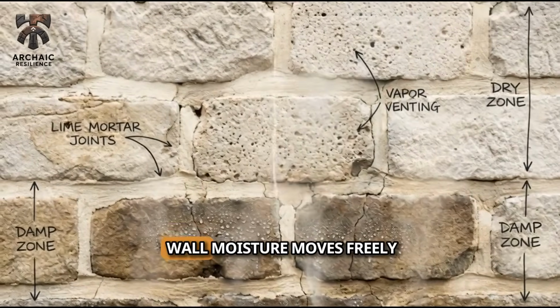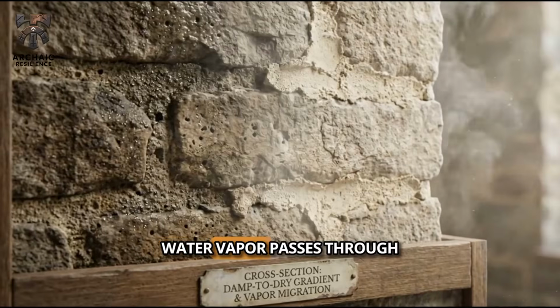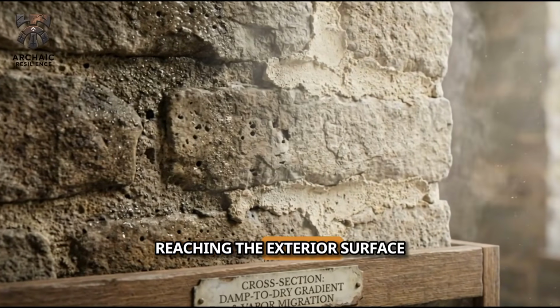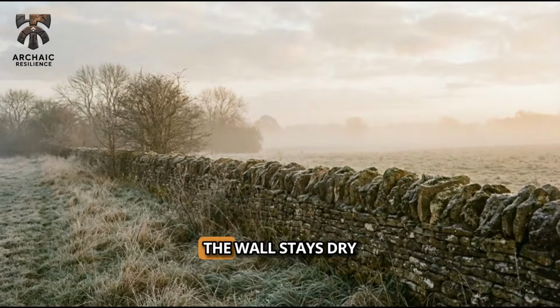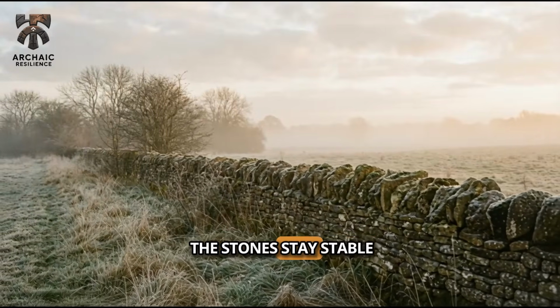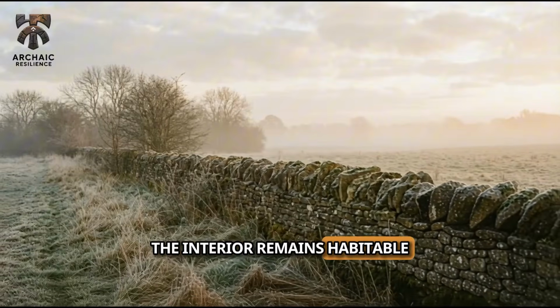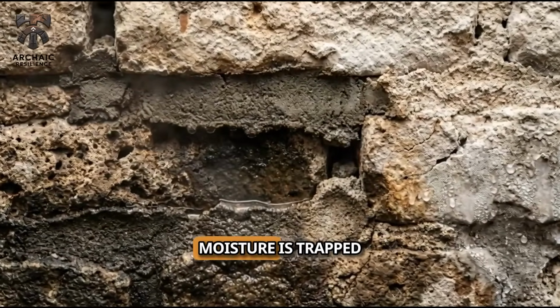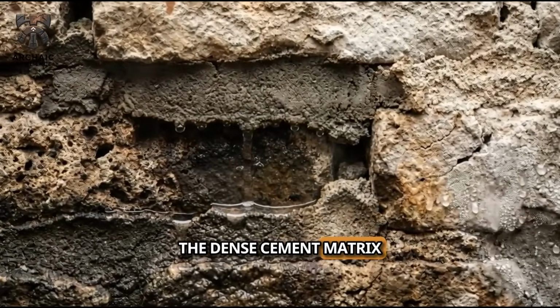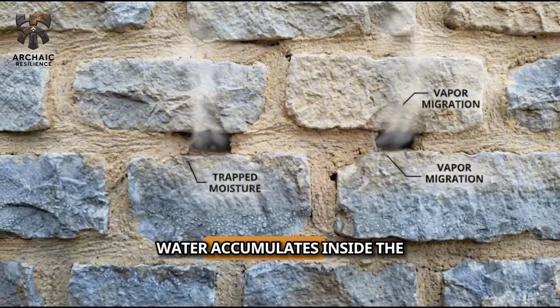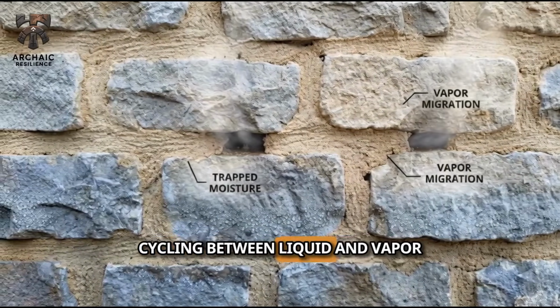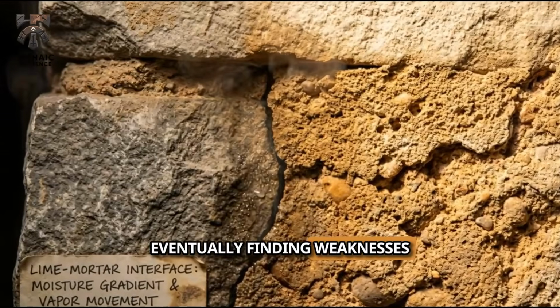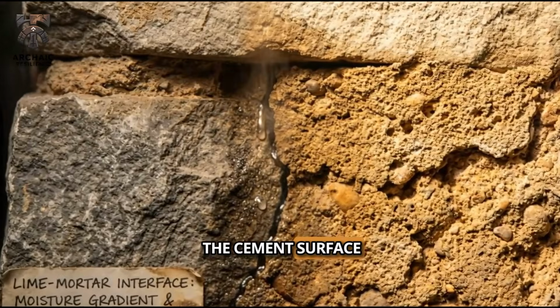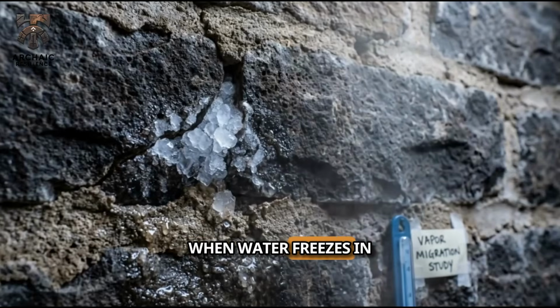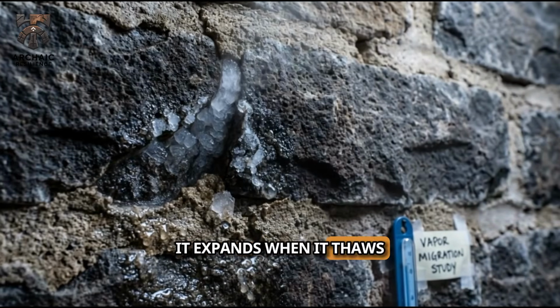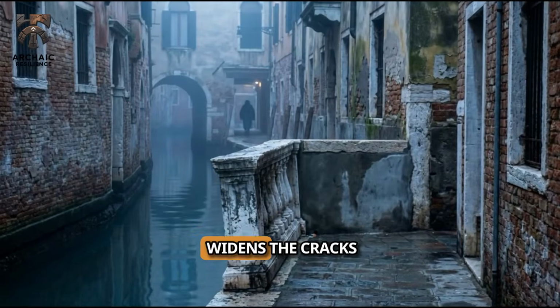In a lime mortar wall, moisture moves freely. Water vapor passes through the mortar joints, reaching the exterior surface, evaporating into the atmosphere. The wall stays dry. The stones stay stable. The interior remains habitable. In a Portland cement wall, moisture is trapped. The dense cement matrix blocks vapor transmission. Water accumulates inside the wall structure, cycling between liquid and vapor, eventually finding weaknesses, hairline cracks, gaps in the cement surface, interfaces between cement and stone. When water freezes in these spaces, it expands. When it thaws, it contracts. Each cycle widens the cracks.